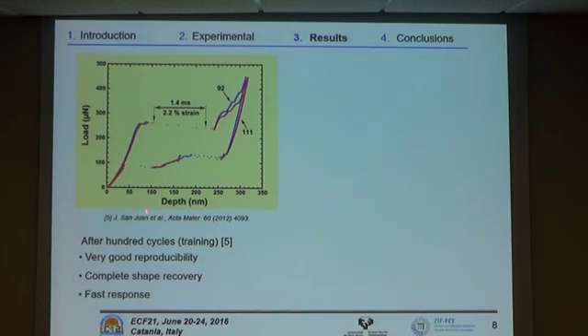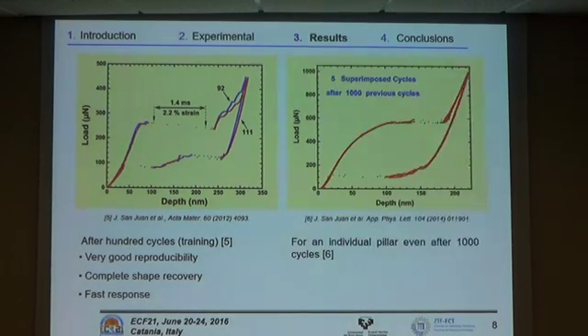In 2012, Professor Juan showed that after 100 cycles, an individual pillar had very good reproducibility, a complete shape recovery, and a quite fast response. Afterwards, we went further up to 1,000 cycles, and again, it has been seen that the properties were maintained. But of course, we need to go further and to have some statistics, and that's why we prepared these arrays and we studied them in detail.